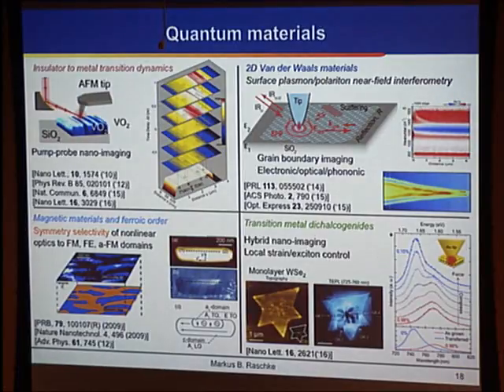Because what's interesting here is that we can push the technique one step further, not just looking at the optical aspect, but combining it in a more hybrid imaging fashion where we control the exciton emission by using the tip, in addition to being an optical probe, also as a nano-mechanical probe. And by slightly pushing into the sample, we can, through control of the local strain, shift the exciton resonance, which tells us which of these factors, whether it's strain or defects, control the exciton frequency and the